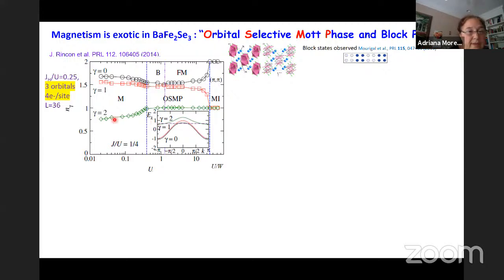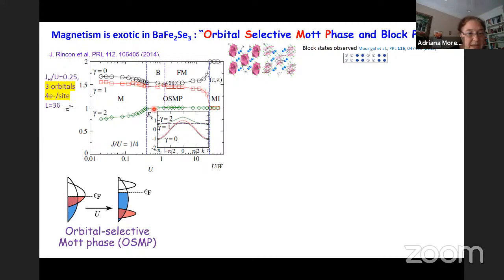What we found is that at small U, all the orbitals are metallic, but as we approach U close to the bandwidth, the green orbital becomes half occupied, while the other two have a filling of about 1.5. So we can think that if that happens, we may be in the orbital selective Mott phase, in which one orbital develops a gap while the others remain metallic.